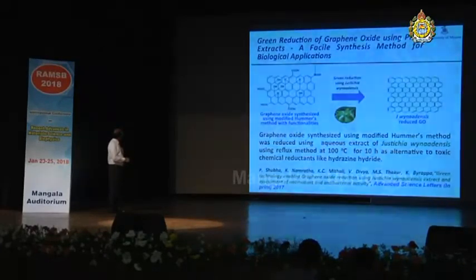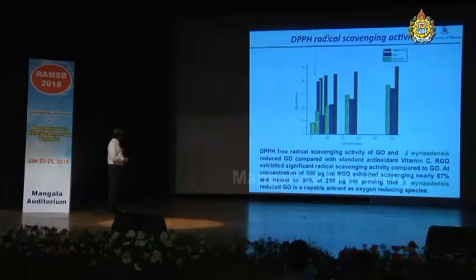And this is the green reduction of graphene oxide using plant extracts, a facile synthesis method for biological applications. This is a very popular herb used commonly as a medicinal plant in cool areas. And particularly they plant it during August, middle of August, that's what I was told. It cures several diseases. And we have taken the extract of this and used it in the synthesis of this graphene oxide and tested it in some biological studies. DPPH radical scavenging activity of this reduced graphene oxide prepared with this herb has been tested here.